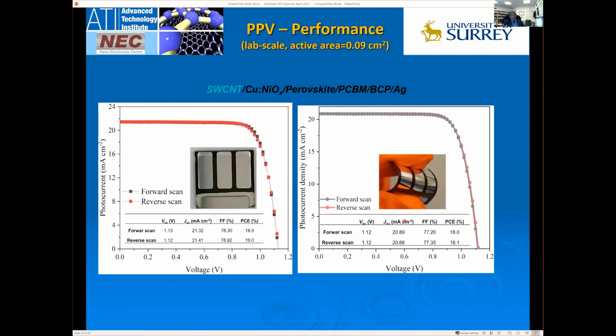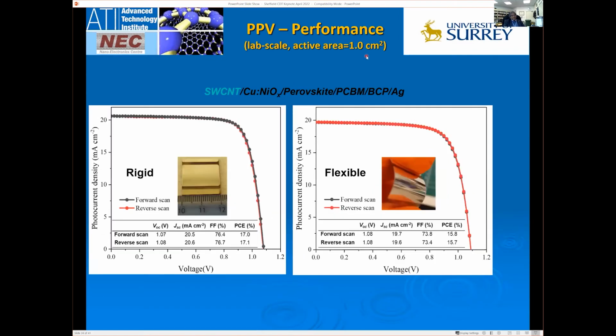If we then replace your ITO with single wall carbon nanotube, I noticed there was a talk previously on using single wall nanotube as transparent conductors. So we save on using indium. We can now go to around 19% power conversion efficiency on rigid substrates and 18% on flexible substrates. But again, you notice that these are quite small areas. If we try to scale up further to 1 square centimeter, you drop another couple of percentage points on rigid